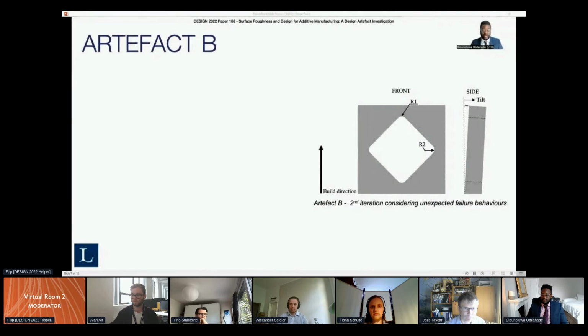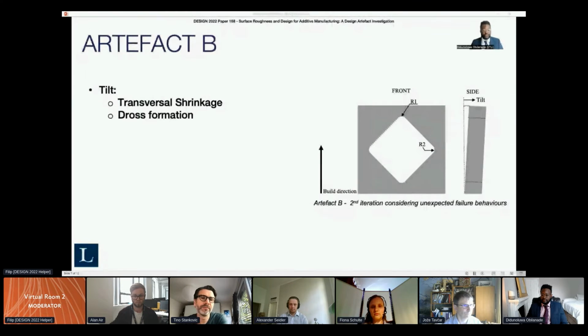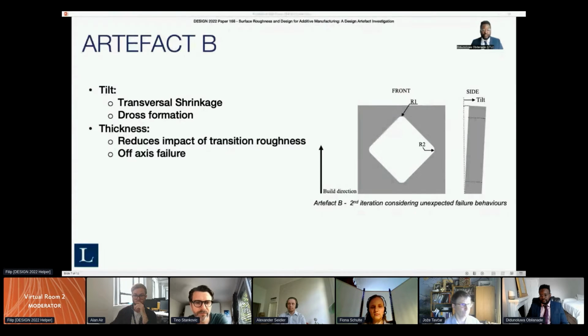To account for these unexpected failure behaviors, a second iteration, Artefact B, was designed with two major design changes to better focus the artifact on the studied uncertainty. Firstly, a tilt was introduced to counteract the impact of the transversal shrinkage and reduce the dross formation at R1. With a tilt, the R1 junction plane gradually connects over several layers, reducing the impact of thermal stresses as these layers cool. Additionally, Artefact B's square geometry should address the R2 off-axis failure due to the transition roughness by causing the failure to occur where the arm thickness is smallest.